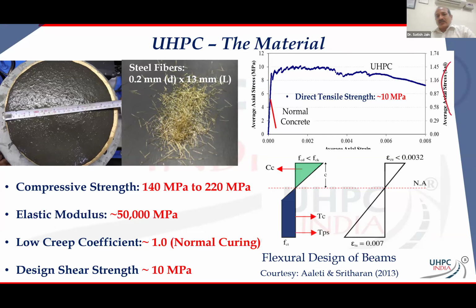But the biggest beauty of all, why I believe UHPC is being used, is the design shear strength. The design shear strength is very high. Imagine, not having any rebar and having just the fibrous UHPC, you may be able to reach about 10 MPa or even 11 MPa in your design shear strength. Plus, then you add rebar. Now compare it with concrete if you want to.